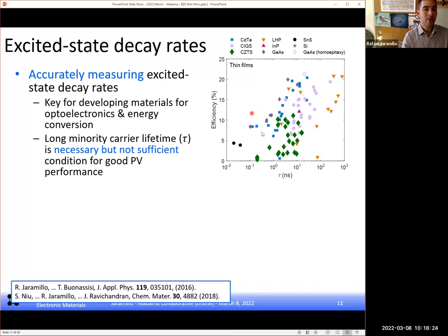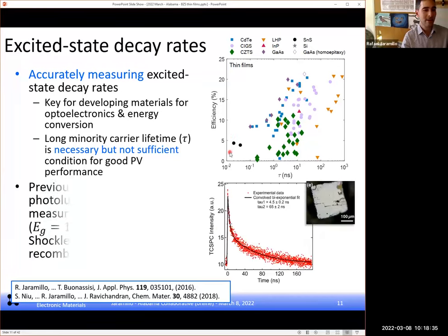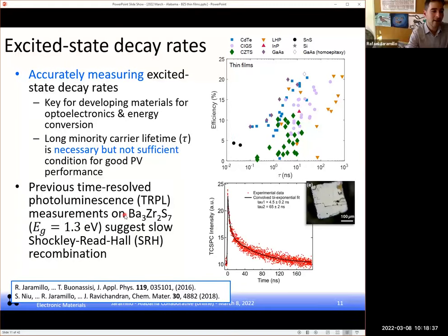Now, when I made this plot, we had just engineered these tin sulfide solar cells. So we made the best darn solar cells from 50 picosecond lifetime materials that I think anyone will ever bother to make. But now we're focused on different materials. So now we're looking at the chalcogenide perovskites. We had some preliminary data suggesting that they have very slow defect-assisted recombination, which we published in 2018. And so we thought we should look at this in more detail.